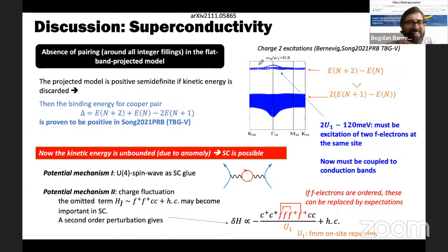So what we proved is that for the charge 2 excitation in the system, there is no bound state. You cannot have a bound state. So Cooper pair does not exist purely because of interaction elements in the interacting Hamiltonian, because of non-commutativity. You have to have some kinetic energy for Cooper pair to exist. You can prove by positivity, basically positive semi-definiteness, that you cannot have a bound state here. So in projected models, you couldn't get superconductivity. You need to add kinetic energy.